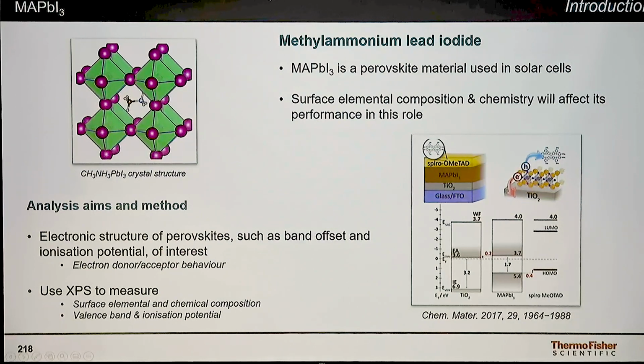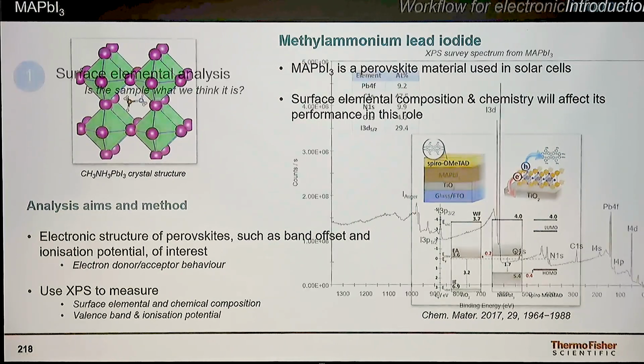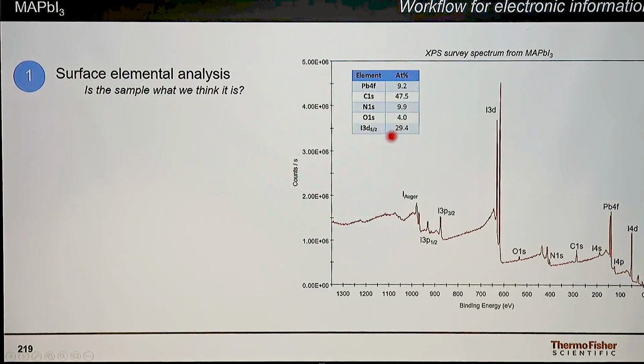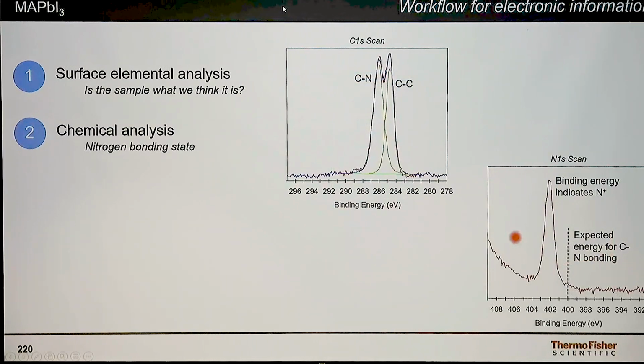Another one is methyl ammonium lead iodide, and that's, again, the same kind of process to understand this. So determine the surface chemistry, a lot of carbon present here because it's got the methyl component. Then we've got iodine and lead. And again, check the chemical state information. So we're expecting carbon-carbon and carbon-nitrogen. But what is interesting actually with the nature of this particular material is that the nitrogen is in a slightly different chemical state because of the electronic properties of the nitrogen within this particular structure. And so we'd expect the peak to be about here, but because it's actually in a charged state, we see it at slightly higher binding energy.